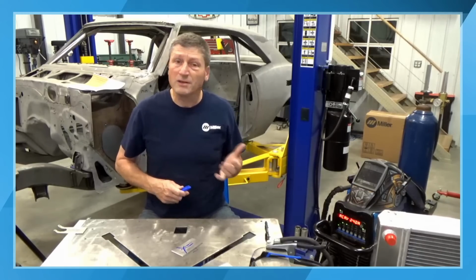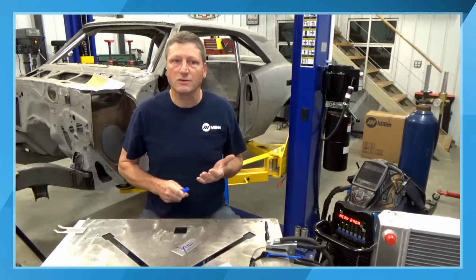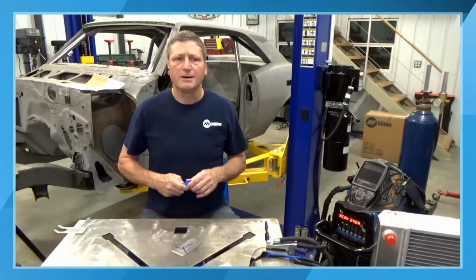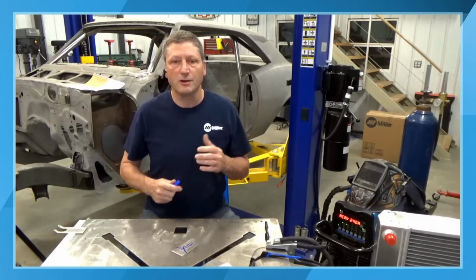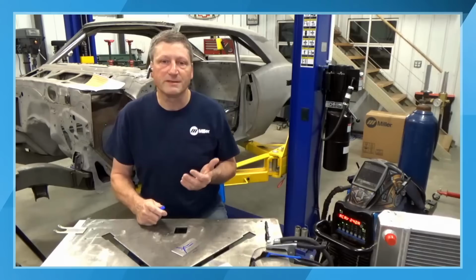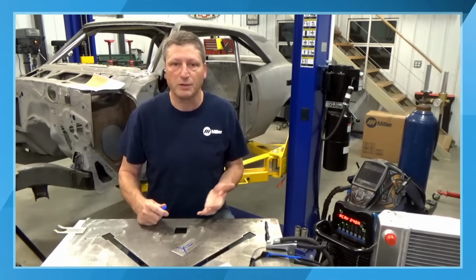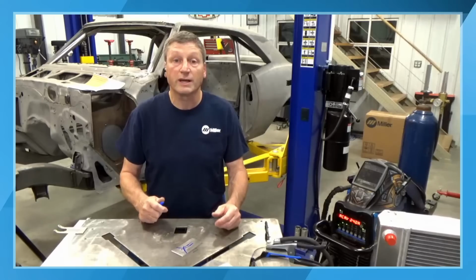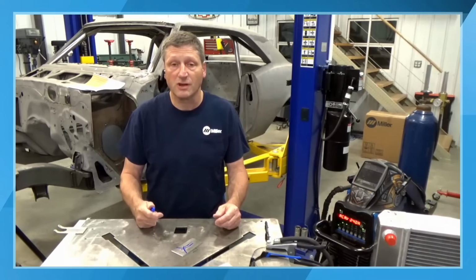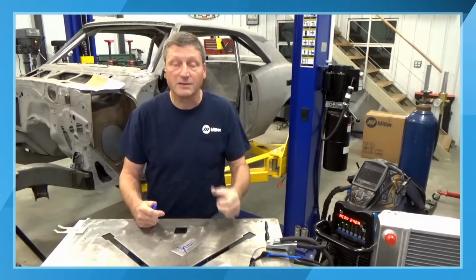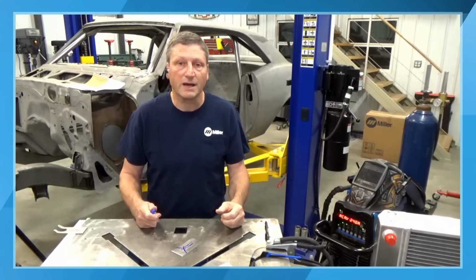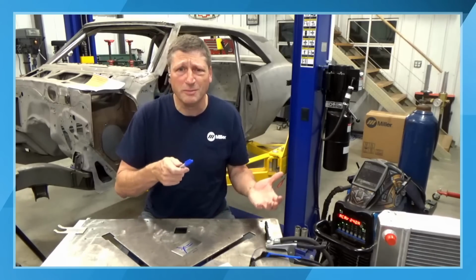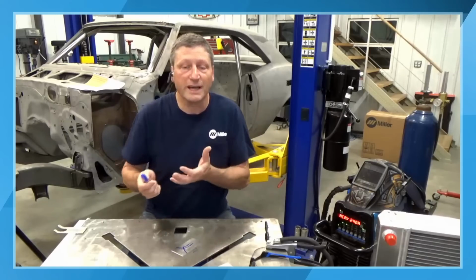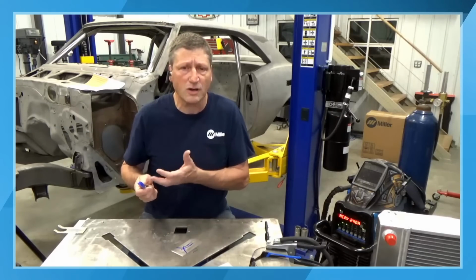If you primarily use AC, you could also use lanthanated, which has higher performance than, say, a green tungsten, which is pure tungsten. We don't recommend putting pure tungstens in the inverters at all. They can't handle the advanced sine waves that we're putting out on the machine. Think of pure tungsten like pure aluminum. It's kind of useless until you alloy it with other elements to make it stronger.